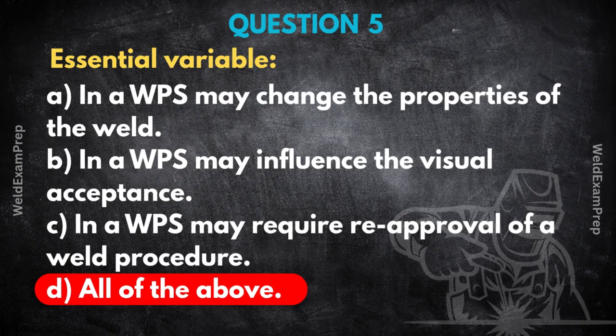What's a common essential variable change you see causing problems or leading to requalifications out in the field? Any common misunderstandings about what's essential versus non-essential? A very common one is changing the welding position significantly. Say, a WPS qualified only for flat position welding. Trying to use it for overhead welding usually requires requalification. The heat input, puddle control, everything changes.